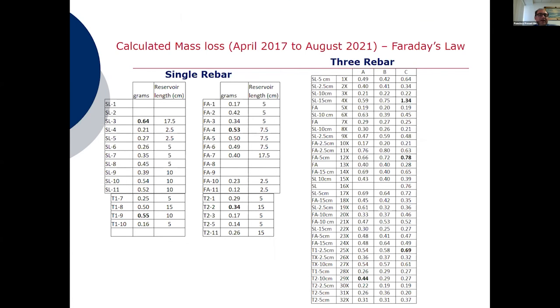As a summary in here, and I'm not going to go over each one of them, here is where we are currently as to the mass loss on each one of the rebars for the period between April 2017 and August 2021, using Faraday's law. What I want to point out is that there is a case in which the mass loss is more than 1.3 grams, whereas the smallest was around 0.14. And research by Torres and Sagüés has suggested that as little as 0.3 can cause cracks.